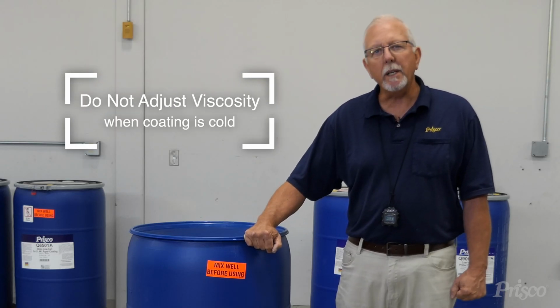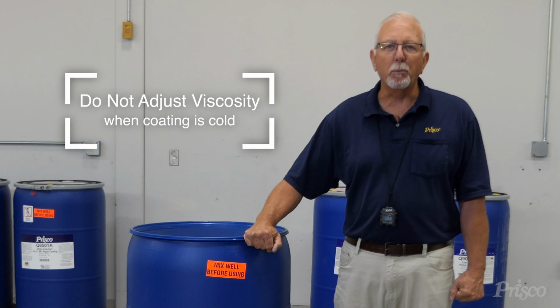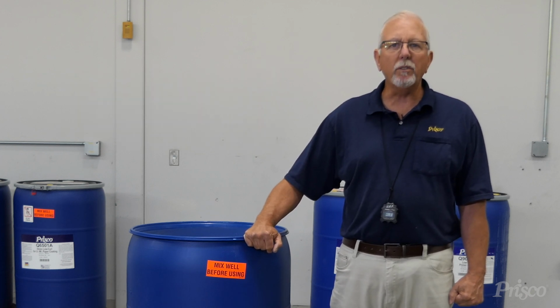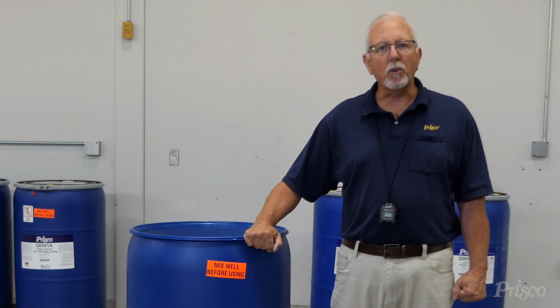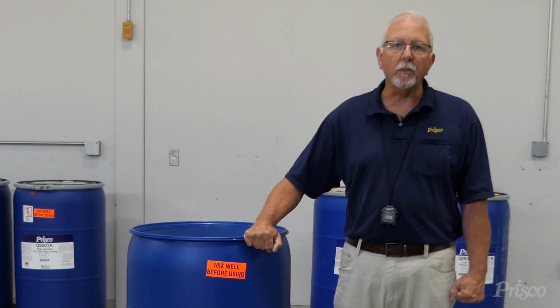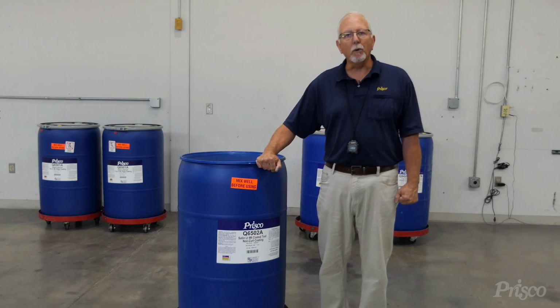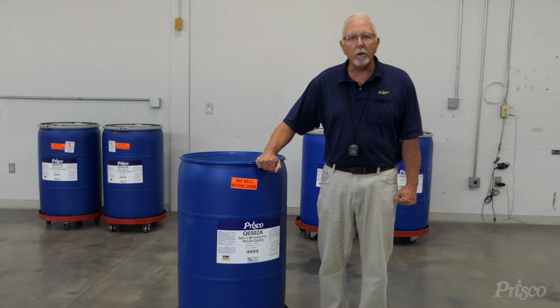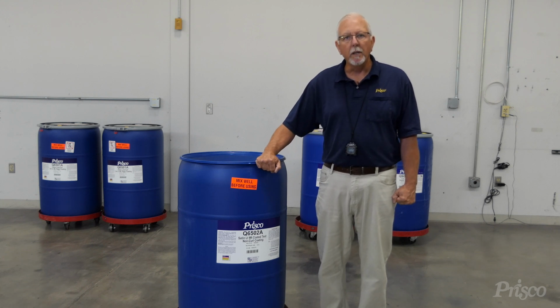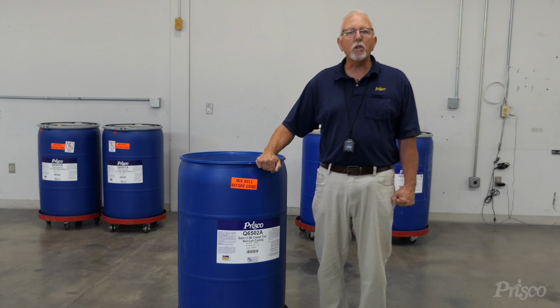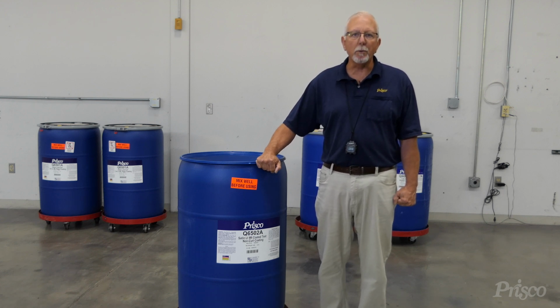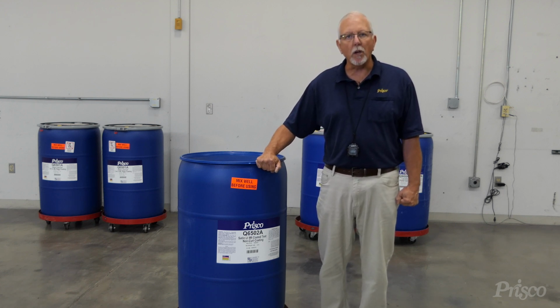Another mistake that's made is they'll bring a drum of coating out to the press, it might be 60 degrees, and they'll go ahead and reduce the viscosity while it's 60 degrees. Then they'll put it on press, it'll heat up to 75 degrees or so, and then the coating's too thin. And once the coating's too thin, you're gonna have all kinds of problems. So make sure that you get the coating to temperature before you make any kind of viscosity adjustments.